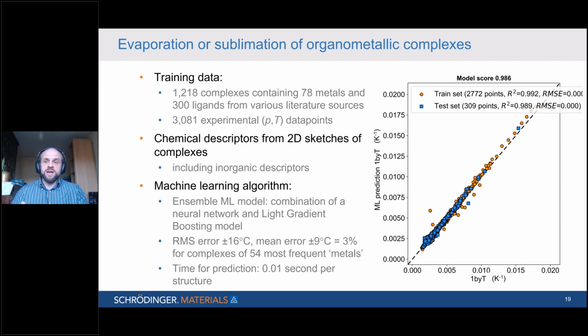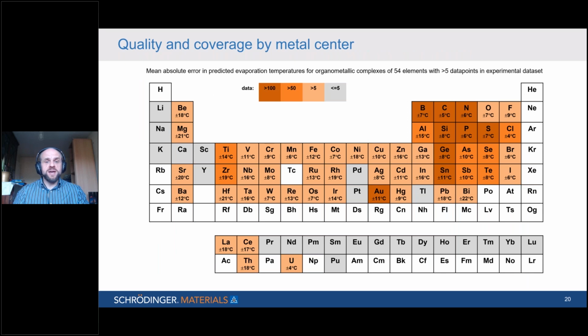We can probably obtain 100 temperatures per second from this machine learned model. So very suitable for screening large data sets. Here's the coverage by element. It's very uneven. The shading here shows the number of data points we had for the different elements in our training set. So this is the set that we used to generate the model.